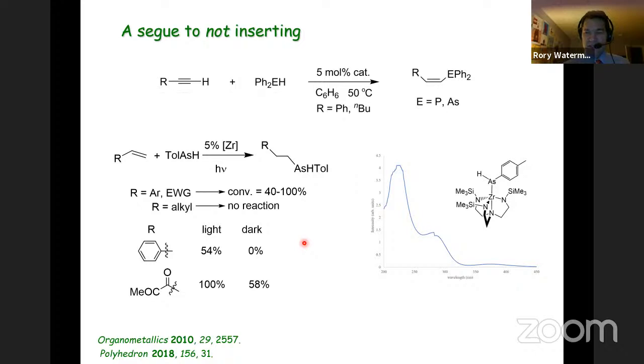So it's not just that this is a more facile reaction. That's absolutely not true, because the control reactions in the dark don't go. But what we did observe is that for a proper Michael acceptor, we saw accelerated reaction in the light. So this is clearly promoted by the photocatalytic pathway that I mentioned before. But in that case, we see reaction regardless of light, suggesting that in fact for arsenes, for hydroarsenation, we have both insertion-based pathways as well as a nucleophilic attack at the zirconium-based arsenido.